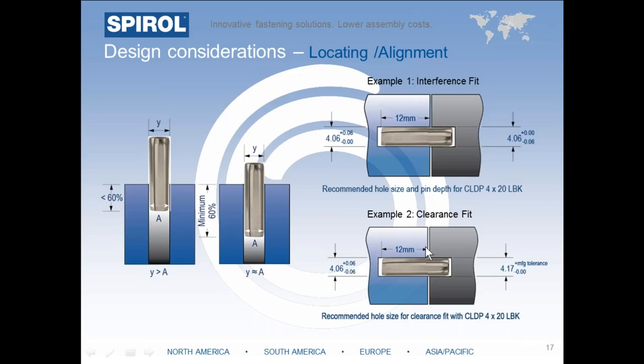In this example, the customer is only looking for a coarse alignment. So we've assigned the full hole tolerance, the 4.06 plus or minus 06, to the primary hole where the pin will be engaged 60% of its length. And we've assigned a larger hole as a minimum in the mating component, in this particular instance, 4.17. And you might ask, why would that hole be larger than 4.12, which is the maximum over here? And again, that's to compensate for spring recovery. So if you want clearance, we have factors we look at that can predict the rate of spring recovery, and we'll compensate that with our recommendations. So here you've got a coarse fit, free alignment, no interference.